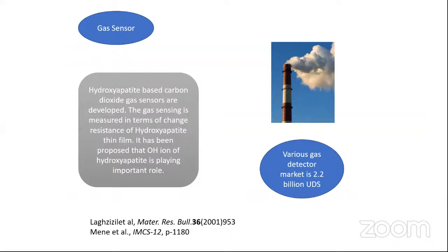Hydroxyapatite-based carbon dioxide gas sensors are developed, and the gas sensing is measured in terms of change in resistance of hydroxyapatite thin film. In terms of changing the resistance, the OH ion plays a very important role. The proposed model is based on the OH ion of hydroxyapatite playing a role in absorption of the carbon dioxide and changing the electrical properties.